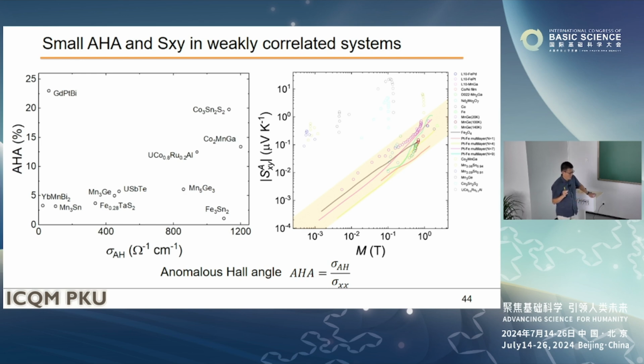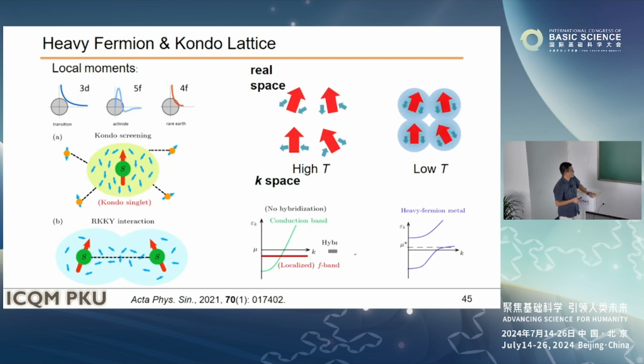Okay, so what we are trying to do from zero. We look around at those compounds, like topological magnets. We notice that the anomalous Hall effect is actually not too big, particularly the anomalous Hall angle, which is defined as anomalous Hall conductivity divided by the longitudinal conductivity. That means how much of the electron current is projected to the transverse direction, right? It's only 20%, meaning you have 20% of the current in that direction. And also the anomalous Nernst effect: if you apply a temperature gradient like 1 Kelvin, then you only obtain about a 10 microvolt difference on the transverse side. So our motivation is to just look around and see what we can have.